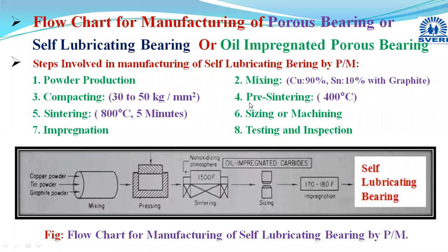And what is the meaning of this pre-sintering? That component or green compact is heated in the 400 degrees Celsius temperature range for a few minutes or a few hours, depending on the shape and size of that component. Then during this pre-sintering stage, what will happen? Whichever graphite we have added in the mixing stage, which helped us to get sufficient lubrication in the pressing stage, that graphite, or any other lubricant you have used, we are eliminating. In the pre-sintering process, by heating that green compact at 400 degrees Celsius, whichever lubricants like graphite or silica you have added are removed, and then that component is given to the sintering stage.